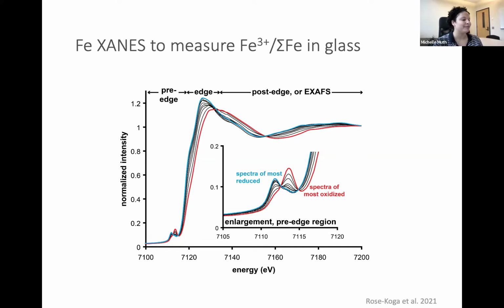Right, okay, thank you. You can do very quick XRF maps on these samples, and for melt inclusions, we normally have to because they're so small that we need to make sure that we're targeting the glassy area. But we do very rapid maps, and we also make sure that before and after the maps are done, there's no point where the beam is sitting on the sample, because we know that anything longer than a few seconds will start to impact the analysis area. So we usually end up driving Matt and Tony crazy because we're very paranoid about getting the shutter closed right after we're done. Understood. Yeah.